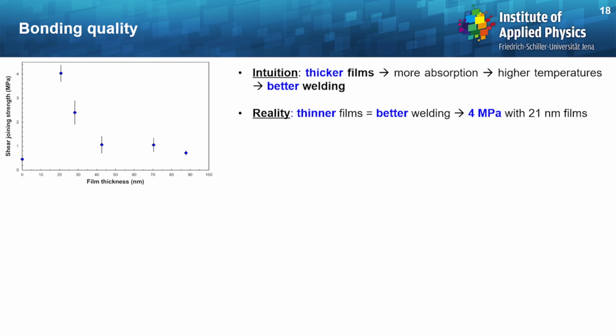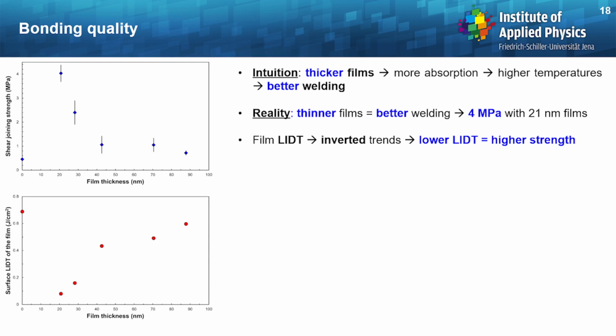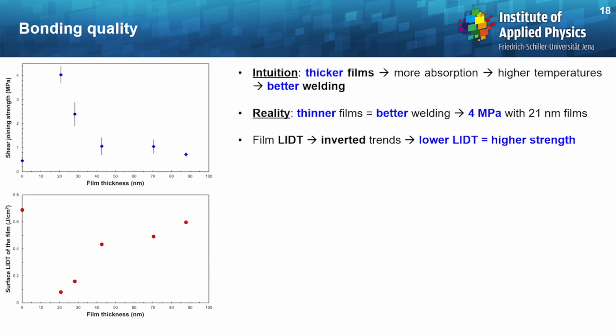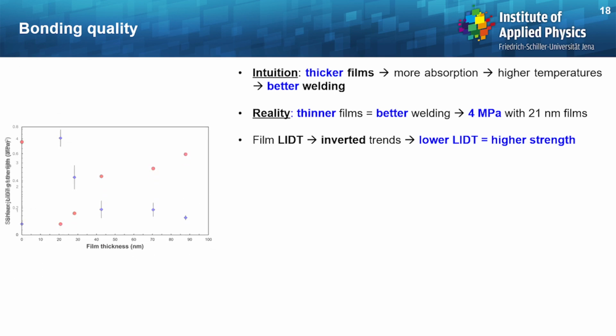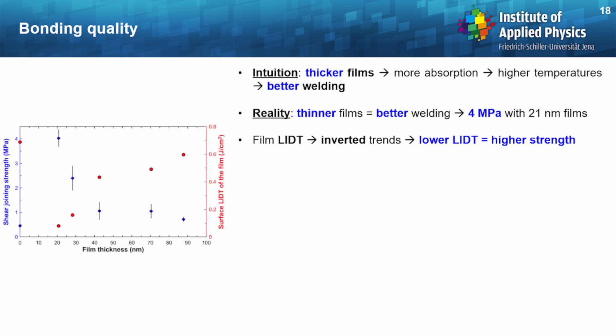In order to explain this, we carried out some laser-induced damage threshold measurements on the films, so only the films, as a function of the film thickness. And you can see that the trends are inverted. The two curves are quite mirrored. And this means that a lower damage threshold means higher strength.